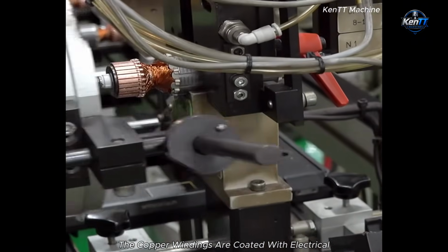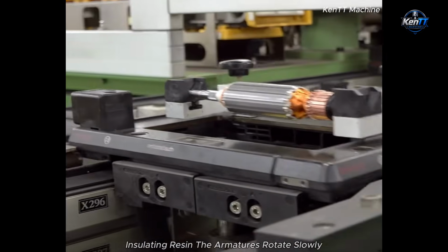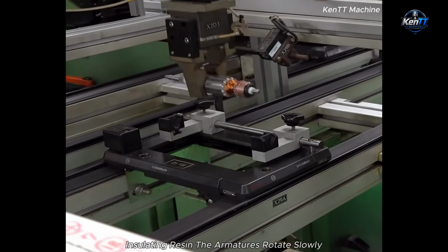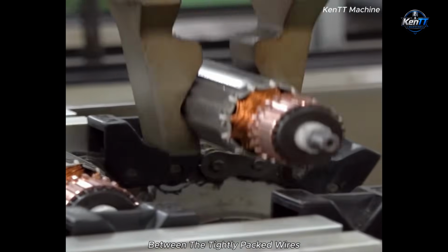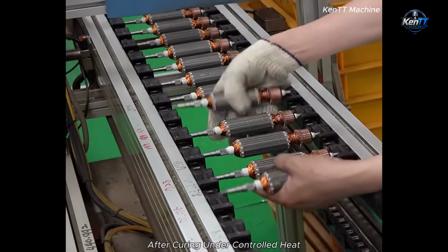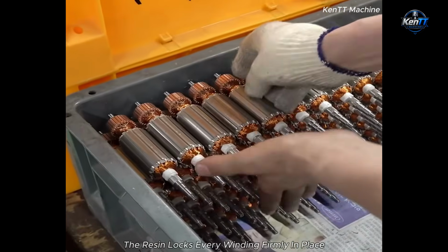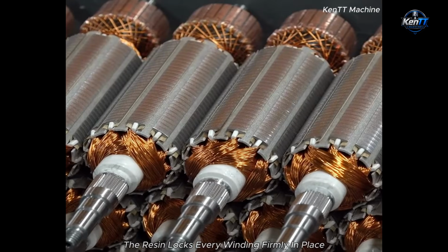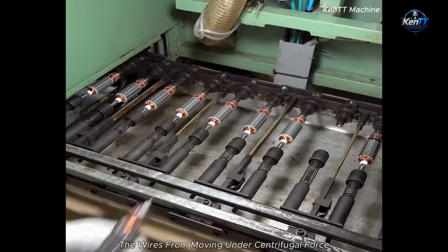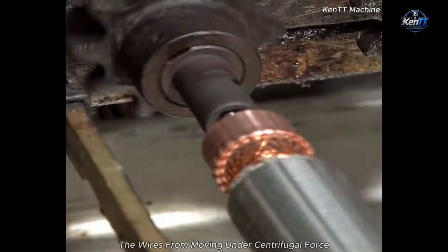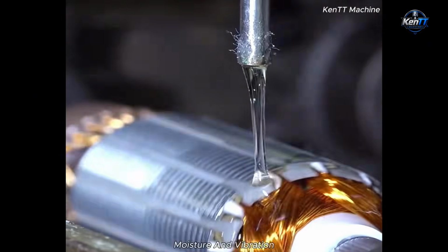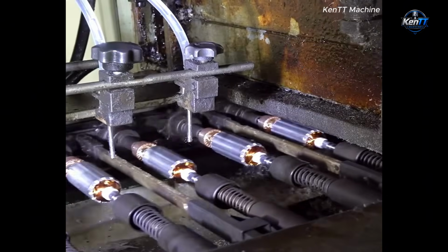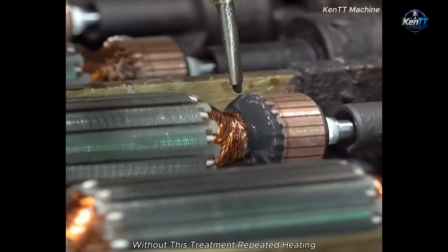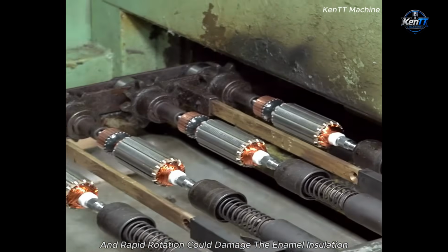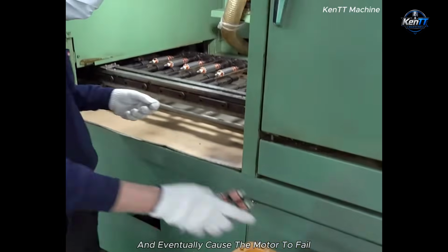The copper windings are coated with electrical insulating resin. The armatures rotate slowly while the liquid penetrates between the tightly packed wires. After curing under controlled heat, the resin locks every winding firmly in place. This prevents the wires from moving under centrifugal force and protects them from dust, moisture, and vibration. Without this treatment, repeated heating and rapid rotation could damage the enamel insulation and eventually cause the motor to fail.